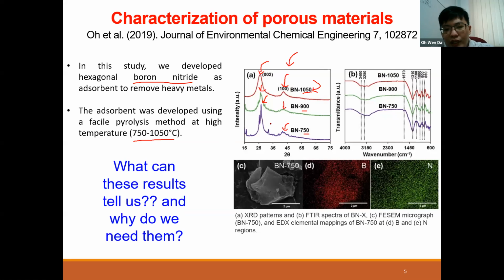But the only difference between these three is that for 750, I have additional peaks coming up. So this shows that indeed I successfully developed boron nitride, but at the lower temperature, 750, the boron nitride has certain impurities. So this is how we look at the XRD data when we characterize it. These are the information that we can get: whether it is a pure boron nitride in this case, or a mixture of something else. So what is this something else? It could be boron oxide. It can be anything, so we have to match it with the library to tell.